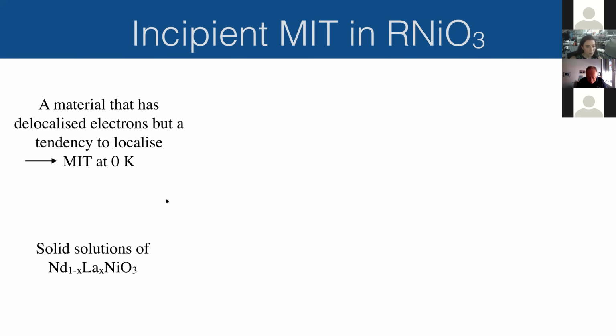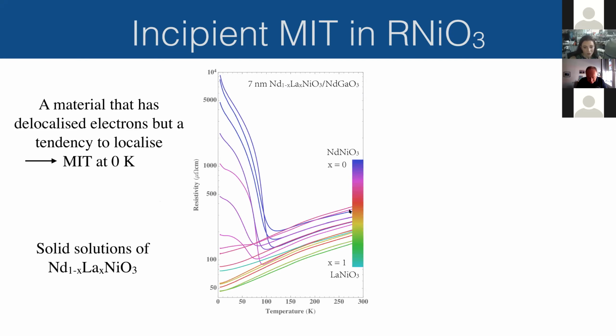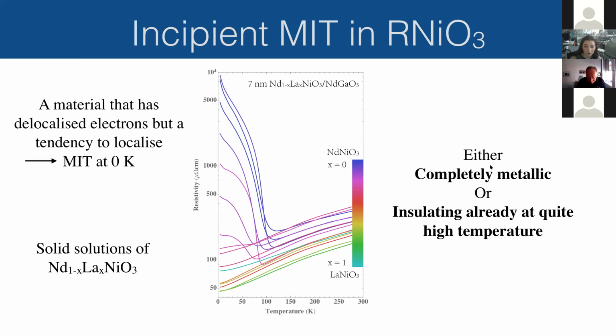So we tried. What we find is that as you change the content, between neodymium nickelate and lanthanum nickelate, you have a metal insulator transition. You have a metal at the other side, but then in between you have a gradual change of the metal insulator transition. But you never see a metal insulator transition close to 0 K. So that didn't exactly work out. Either we have something completely metallic, or we have something insulating that's at quite a high temperature, like 80 Kelvin. So we didn't manage to find an incipient metal insulator transition.